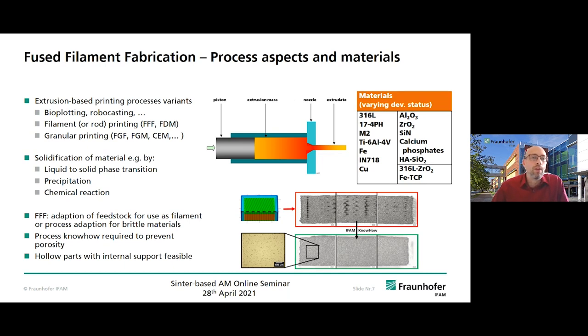And some process aspects. So the fused filament fabrication is an extrusion-based printing process, and there are many of those. Actually, the very early ones like bioplotting and robocasting mainly make use of slurries. Then there's, of course, the filament-based printing, which can also be a kind of rod that, when it's more stiff, has to be adapted printer-wise to be able to use rods that are more stiff than filaments. And as mentioned before, also granular material may be used, for example, in these granular printing processes. And these different processes may make use of different solidification processes. For example, when we melt the material and it cools down, it's a liquid to solid phase transition,